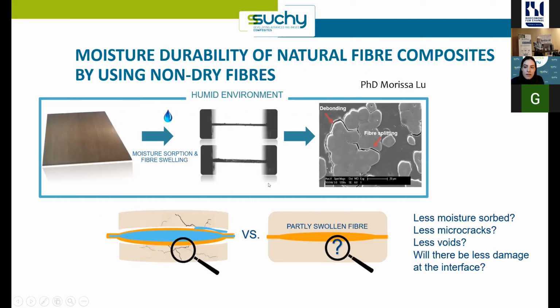So the idea is that if you don't dry the fibers, you would create less damage in your composite. Because normally you go from the fully dry condition during production to quite high humidities, you will really get swelling of the fiber, and you see all these kinds of defects appearing, debondings, fiber splitting. So the idea was, if the fiber is already pre-swollen, it will be more in equilibrium with the real conditions where we use it, because we normally use it between, say, 40 and 85, 90% humidity. So that was the hypothesis that we wanted to test.